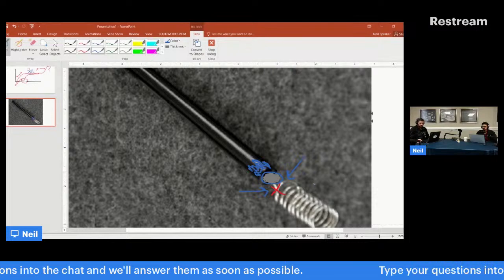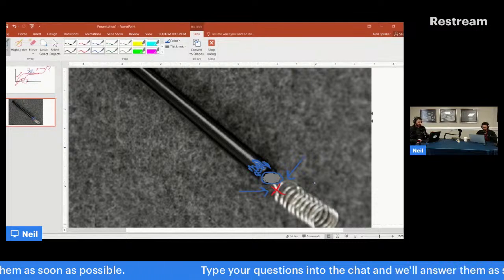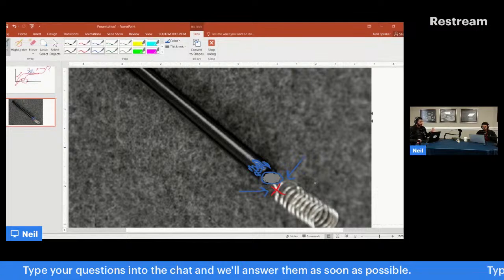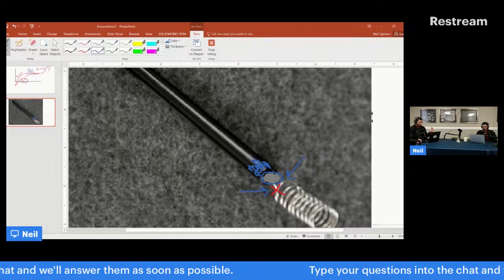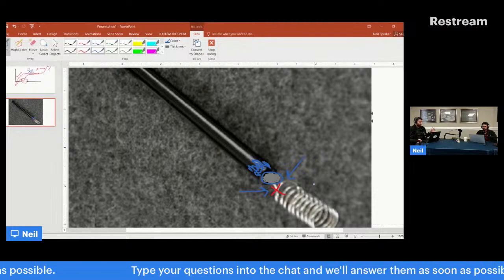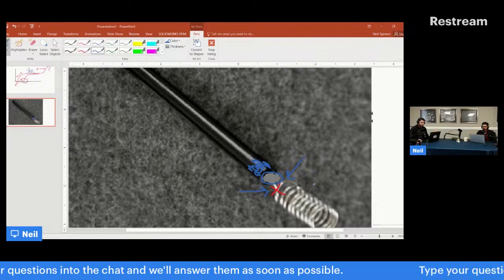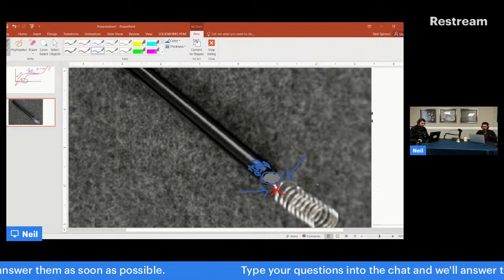And then the third reason, which is less specific to this product exactly, and something that would depend on the application, is that in fixing a severed platinum strip or wire or whatever, you would do some sort of a soldering or brazing application, which usually involves another metal. A lot of times like lead, right? They make lead-free solder now too, but in my experience, it doesn't work as well. So people still do use lead, which is also an electrochemically active material. Maybe people tape it up with copper tape or silver tape, right? The problem with doing that potentially is that you're adding a different conductive material, and now your electrode is no longer a platinum wire. It is a platinum wire with something else.